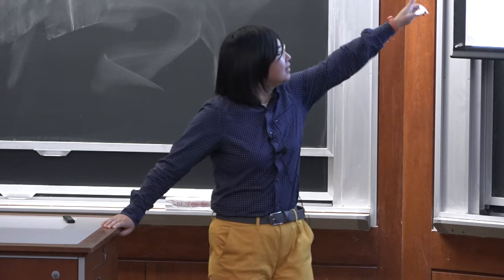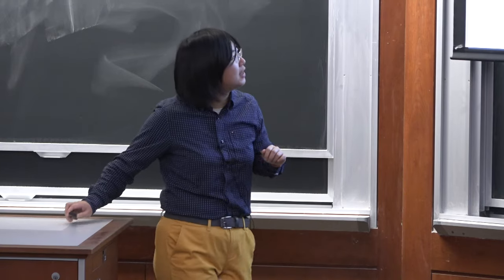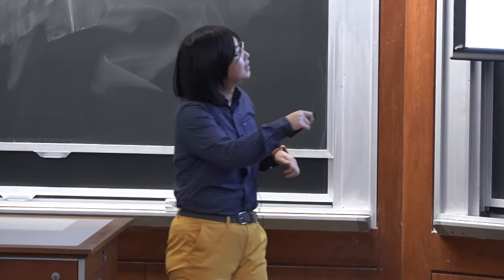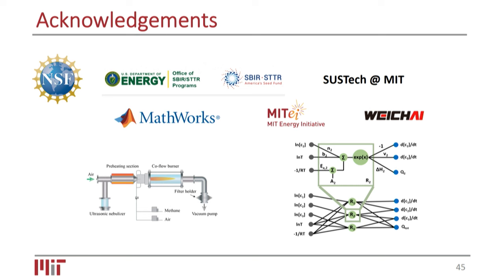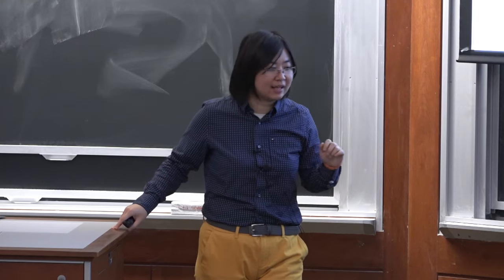I see. So yeah, this figure is a good illustration. I think what Matthias is saying, I want to clarify, is that there are actually two temperature zones. We have a relatively mild temperature zone with a slower heating rate here, and a higher heating rate and higher temperature zone with the flame. So for the evaporation of the droplets, et cetera, we are confined to the slower heating zone rather than the flame zone.